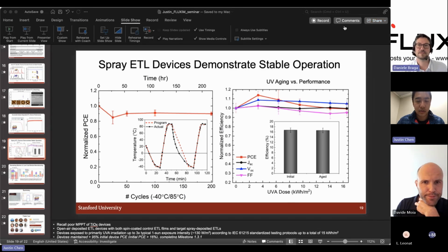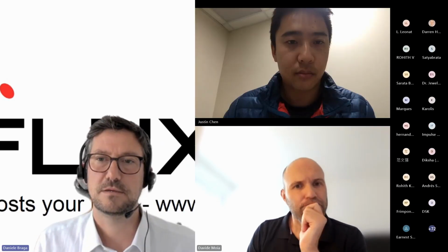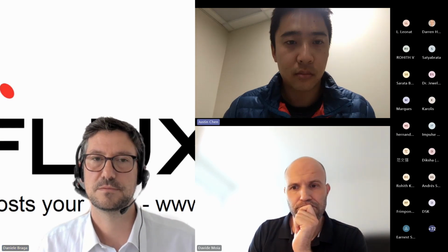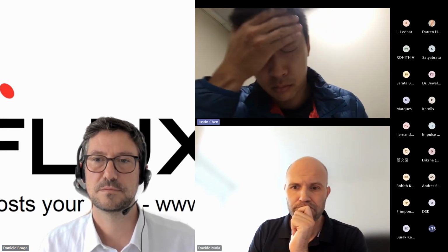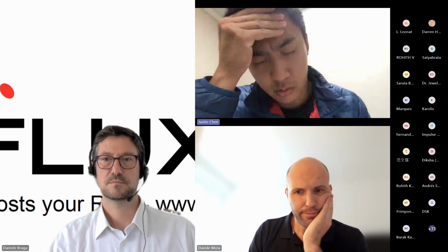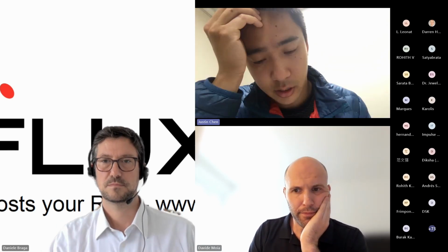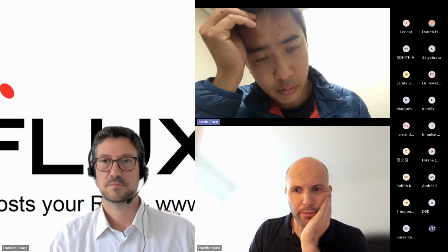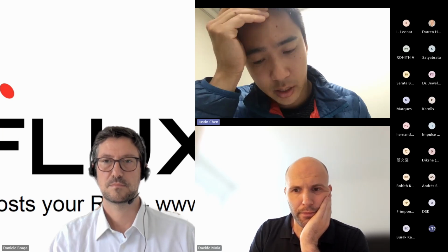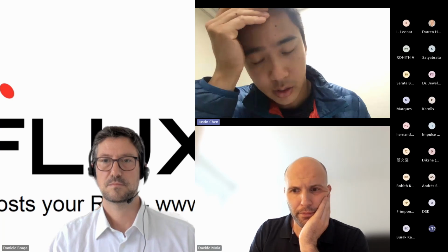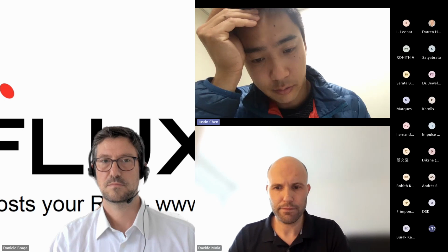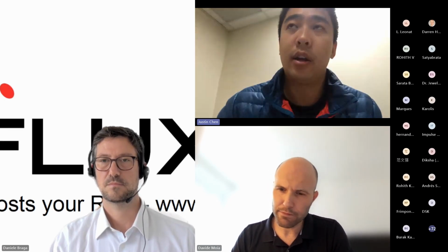Yeah, I think so. They're also asking if you could share the composition of the perovskite. Yes, we use quite a mixed one. It's by a researcher named Qi Jiang. They're based out of the NREL, but it's basically a four cation. So there's a little bit of rubidium, some cesium, some methylammonium, and formamidinium, and a little bit of bromide and iodide.